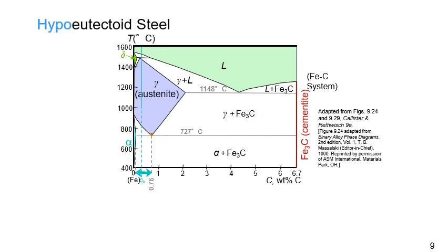Now our line pipe steels will not be fully pearlitic. They won't be at this eutectoid. They will be hypoeutectoid, below the eutectoid, below 0.76% carbon. And just like the eutectoid steel, they start off in the fully austenitic phase, where all the grains are the same, a single phase region.